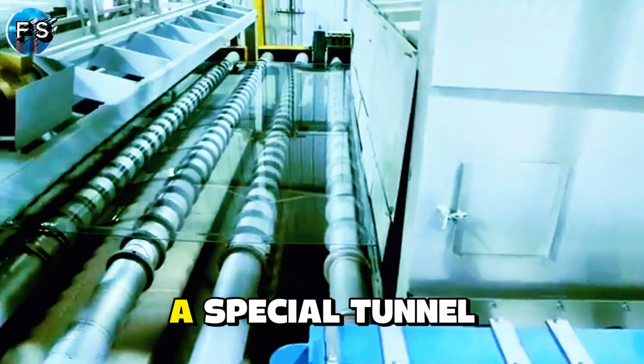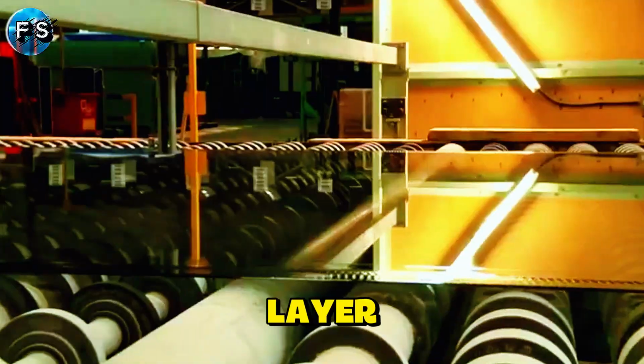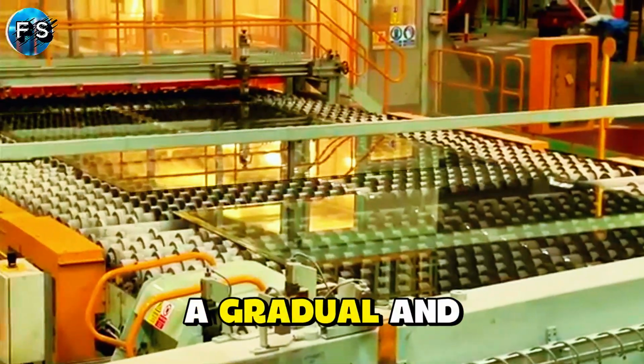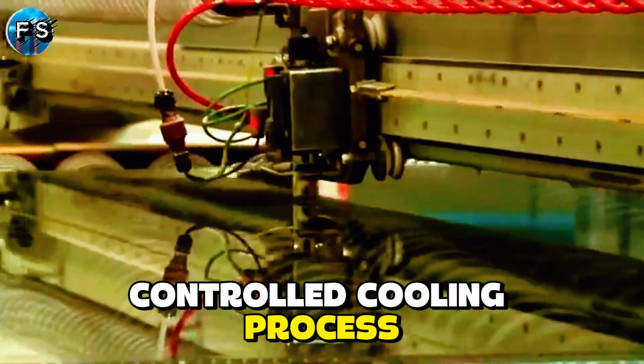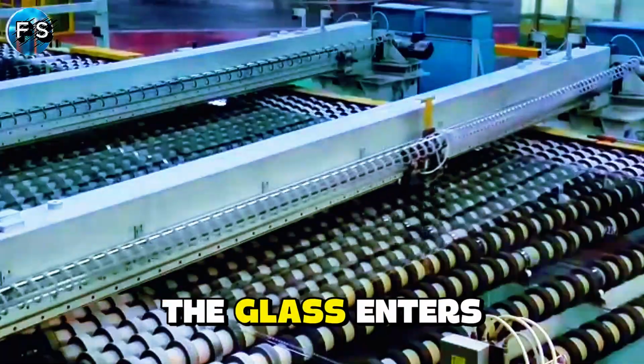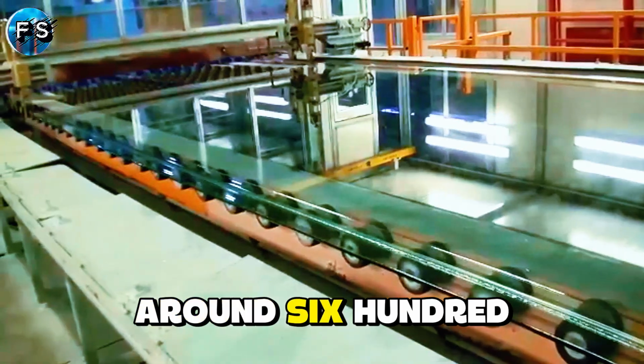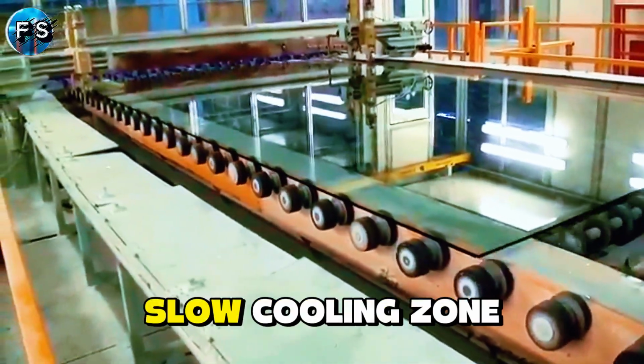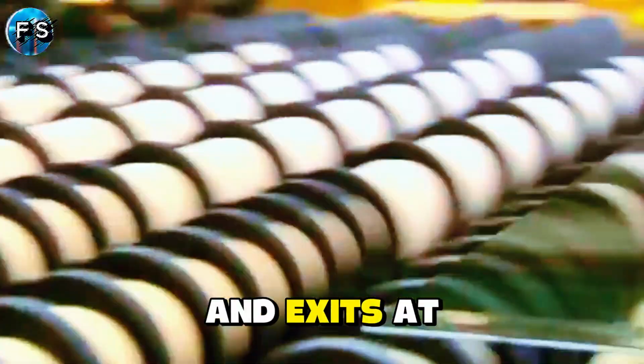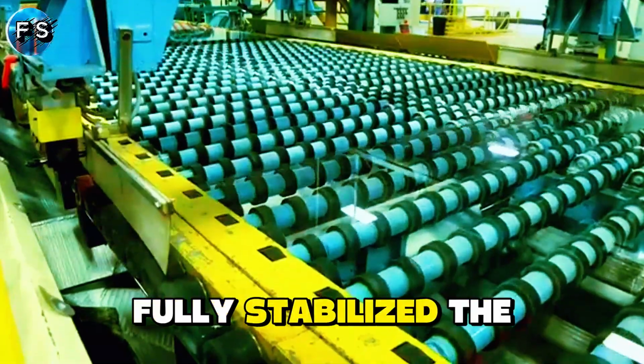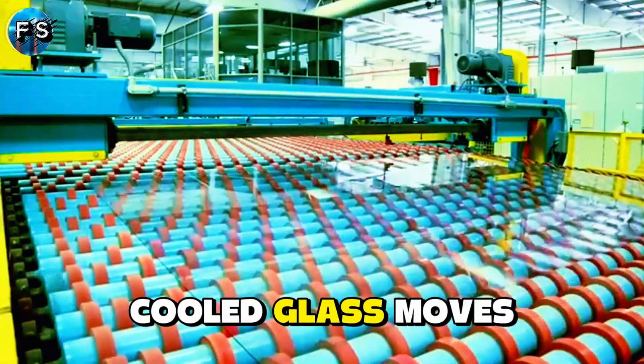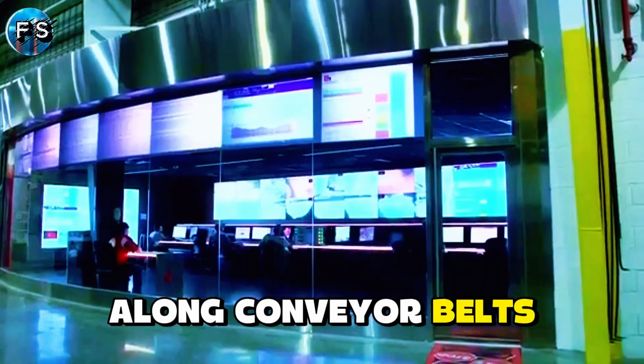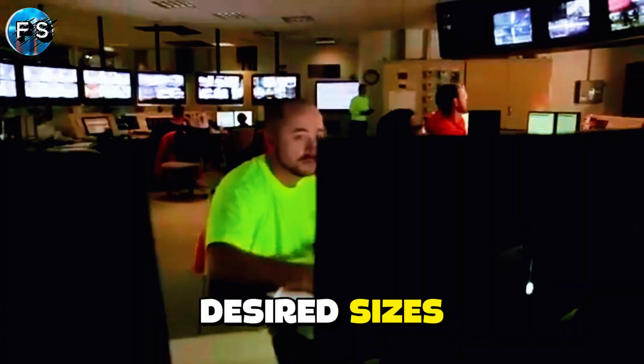It then enters a special tunnel called the annealing lehr, where it undergoes a gradual and controlled cooling process known as annealing. The glass enters the tunnel at around 600 C, passes through a slow cooling zone, and exits at room temperature. Fully stabilized, the cool glass moves along conveyor belts where it is cut into the desired sizes.